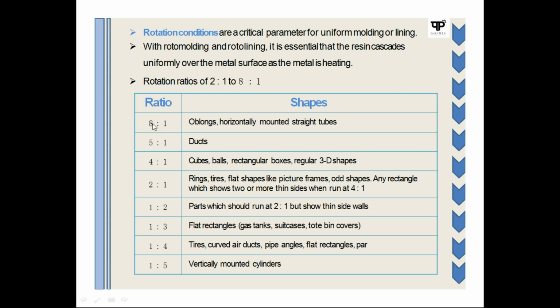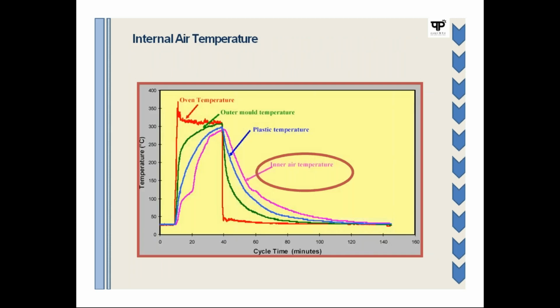Now you can see the ratio is 8:1 for straight tubes, and for ducts like 5:1. So these ratios depend on the shape. Suppose you are designing a new product which does not fall under any of these shapes. In that case you have to do some hit and trial, and from there you can find out the correct ratio required to get good quality of the product.